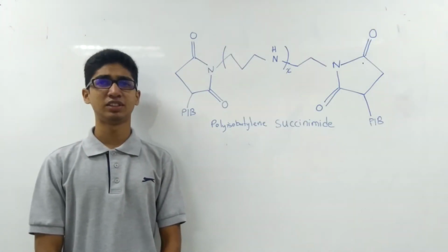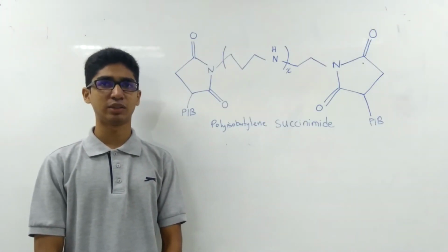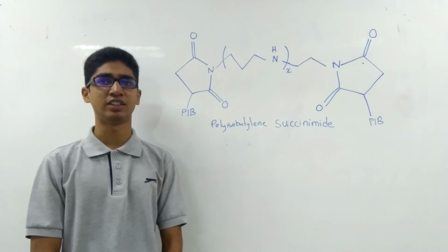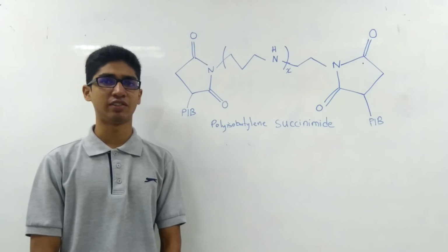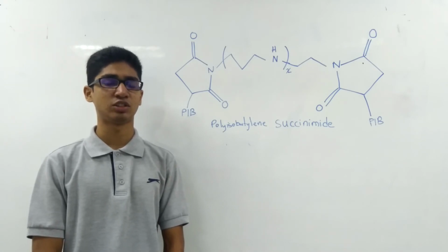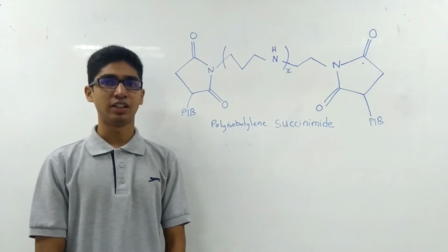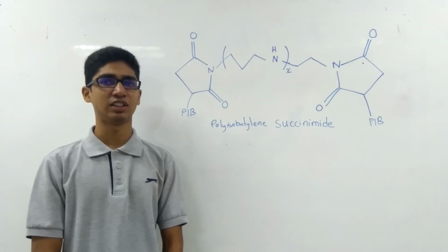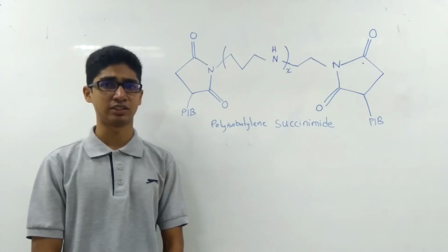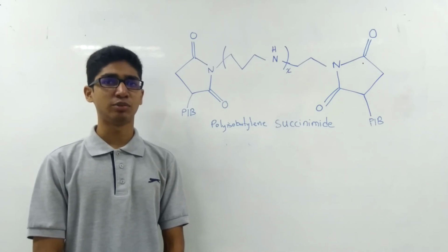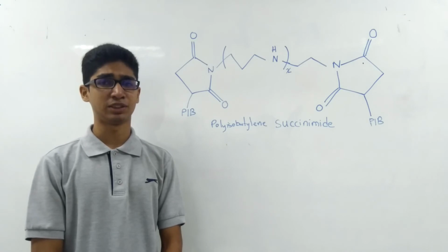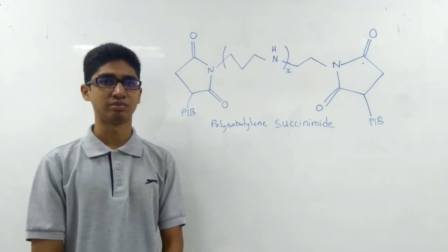Ashless dispersants have longer hydrocarbon tails than the detergents, but function similarly in that they form micelles which trap deposit precursors such as soot or sludge. They can attract and hold at least 10 times more sludge particles than detergent micelles. Polyisobutylene succinimide will be used as the ashless dispersant in our engine oil.